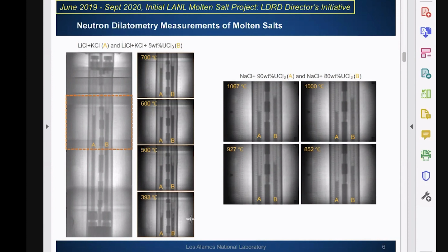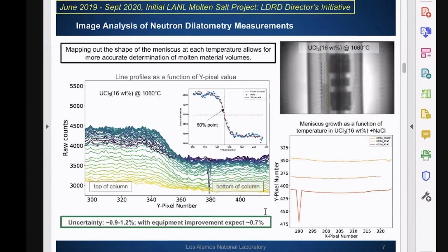So I wanted to point that out because we found that salt wasn't fully molten despite 30-minute soak and exposure time. It actually takes quite a lot of heat energy to fully melt these, and this is something that we also observed in our DSC experiments. So this caused us to change our approach to heat the upper boundary of the experiment and then take measurements on the way back down to the liquidus point of the salt mixture. Just a little pivot there as we were taking data.